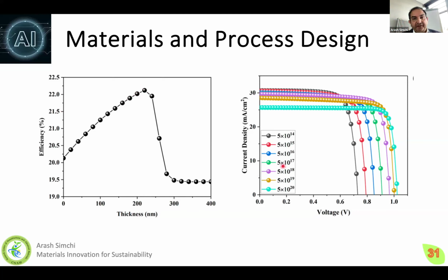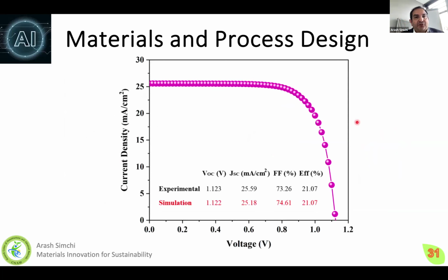On the right-hand side, you see a figure, voltage versus current, depending on doping density. So if we change the doping density of our materials, for example in the hole transport layer, then how will it change? We feed all the data to a machine learning artificial intelligence system and ask it to design a solar cell for us. Here is an experimental and simulation result showing we can reach an efficiency of 21%. Yes, the first try was 22%, but altogether it's 21%. It's excellent. These are relatively sustainable materials that we can use in a very complex system. I wanted to show you how material scientists and chemists have to use artificial intelligence, deep learning, and machine learning for materials design for a sustainable future.